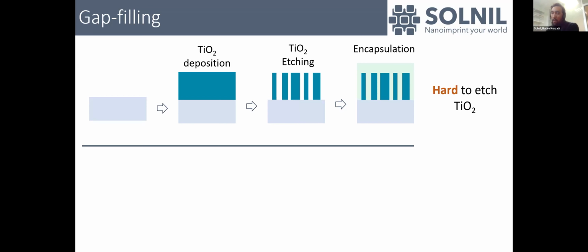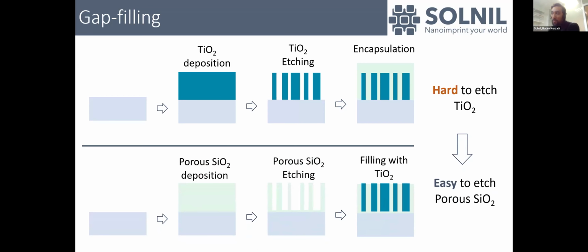So we have been working on another approach at Solnil, where we went the other way around. What we did first is, because our materials are liquid, can we just make holes in silica instead, because silica is very easy to etch, especially porous silica. So you can very easily etch very deep grooves into silica. And then you keep using our material, which is liquid, and we can fill the gaps. This is what we have been working on for the past year.